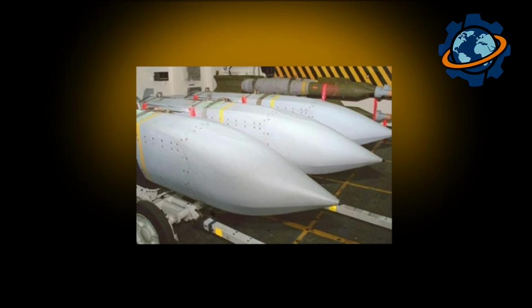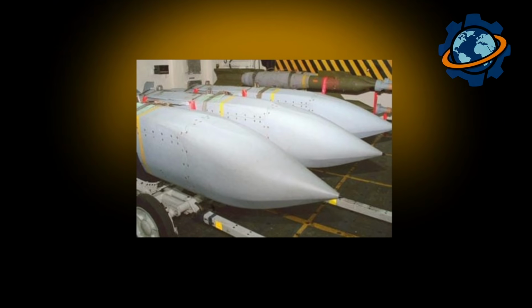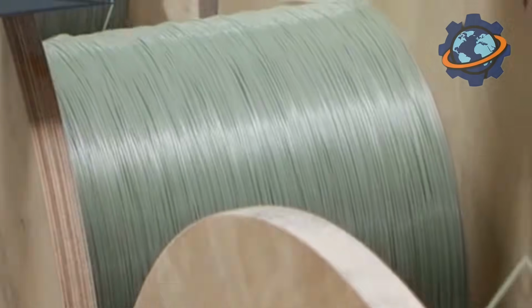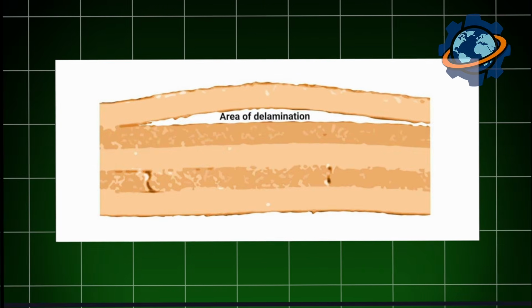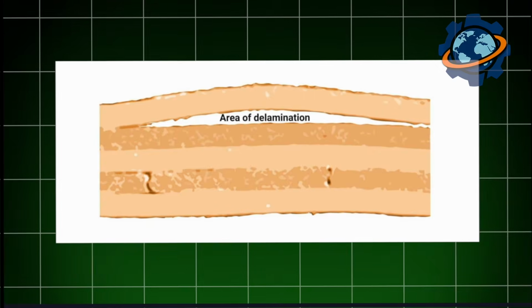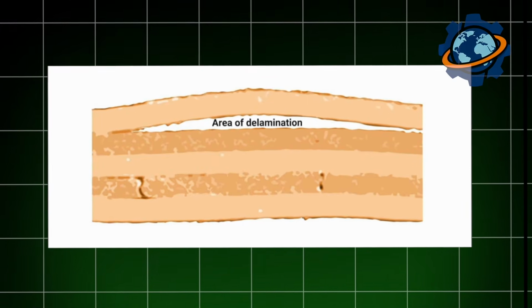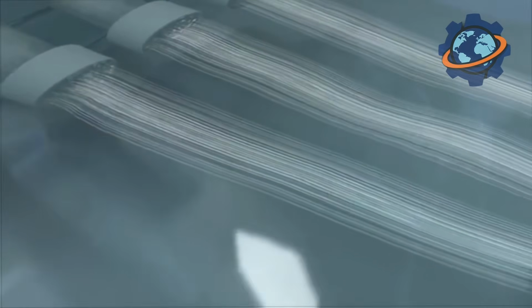Modern aerospace composites achieve interface strengths exceeding 12,000 pounds per square inch, meaning the bond between fiber and resin is stronger than many metals themselves. This step is critical because composite strength depends not just on fiber properties, but on load transfer efficiency from matrix to fiber. Poor surface treatment causes delamination, layers separating under stress, the characteristic failure mode making carbon composites unravel rather than fracture.